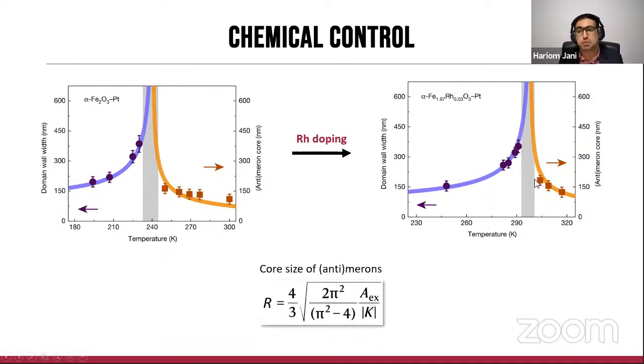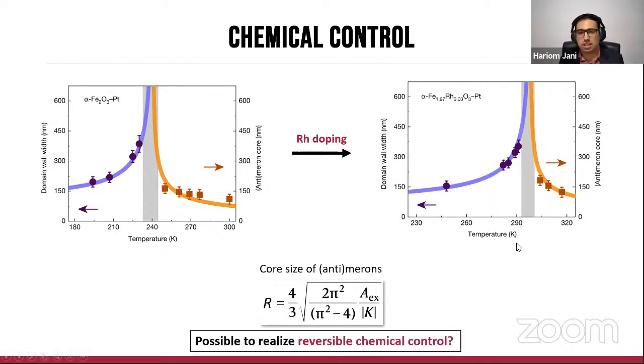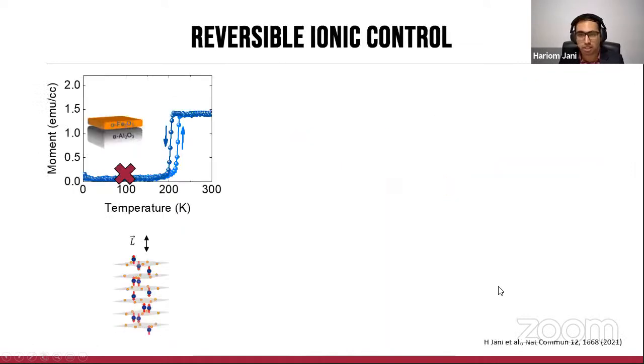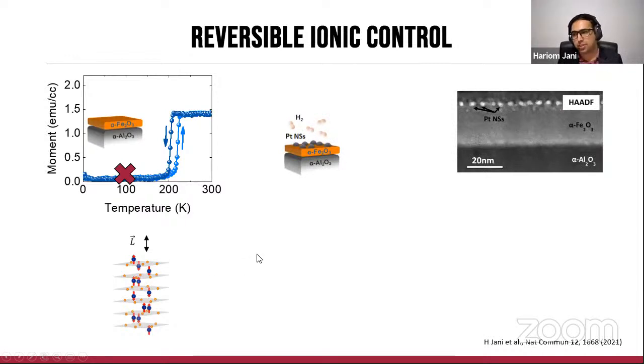What is interesting then is to explore reversible chemical control, and we realize this by doing ionic hydrogen doping in the system. What is shown here is again the pristine samples, and we now perform hydrogen doping by using a process called catalytic spillover. This is a proof of principle approach. So as you can see here, this is still by using gas atmosphere controls, but it provides some very interesting insights that I will just be discussing now.